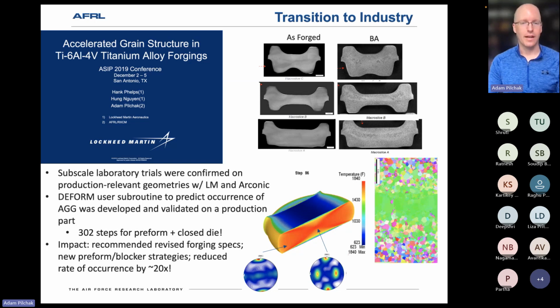Working with Lockheed Martin and Arconic, we actually scaled that up and repeated a lot of those experiments on billets of much larger size, so 8, 10, 12 inches. We also did side pressings at a variety of different initial aspect ratios, which allows you to tune that amount of plane strain compression versus amount of relaxation, I'll call it, where you allow the axial direction to extend as well.